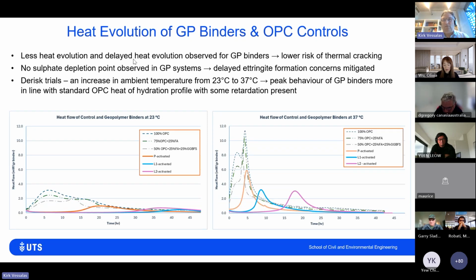A lot of these findings that I mentioned up the top have been summarized earlier, but very quickly, you can see that there is less risk of DEF, delayed ettringite formation, occurring in the system. As I mentioned earlier, there's less thermal cracking present. And if we increase the ambient temperature, we see that the peak behavior comes more in line with a conventional ordinary Portland cement system, but there's some retardation present. So overall, the technology seems to be far more appropriate for releasing less heat and requiring less heat input in the system.